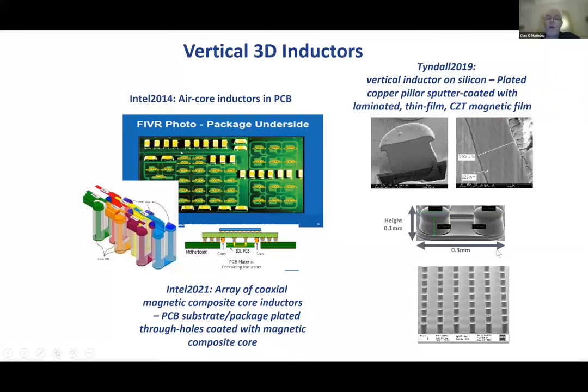So here you have 0.3 millimeter by 0.1 millimeter of total footprint for this. So that's, what is it, 0.03 millimeters squared. And that compares with, if you remember the thin film inductor I showed you earlier, it was 0.3 millimeters squared footprint. So these are tiny. And that would really open up the opportunity in the future. So we are in the process of patenting this technology and trying to iron out some issues that we have with the overall concept. But if we could get this working, then that would be really cool.